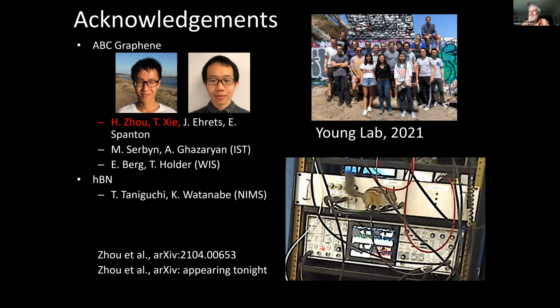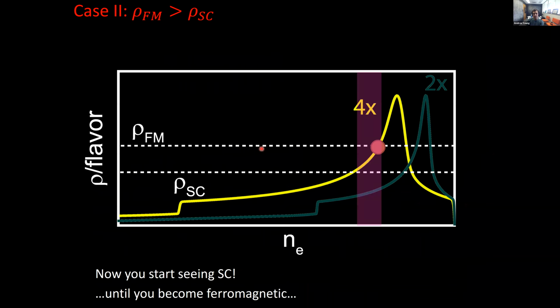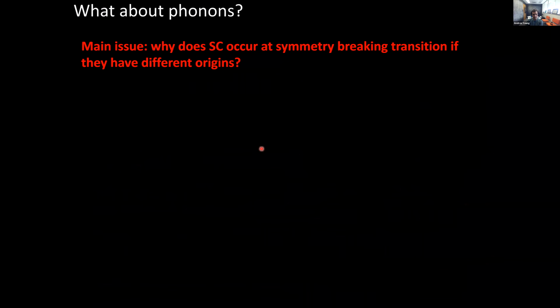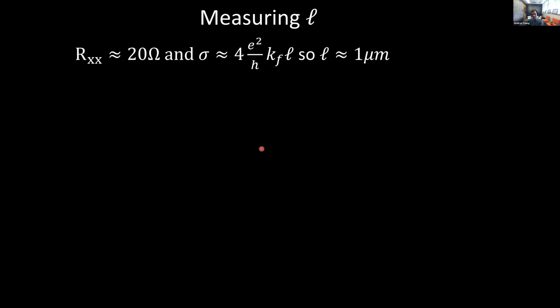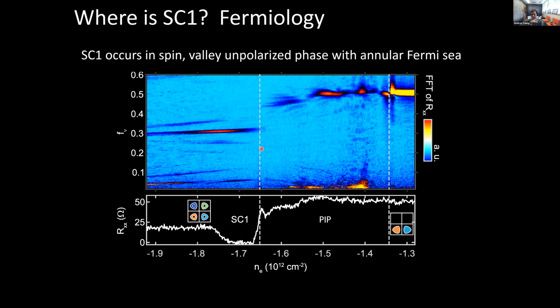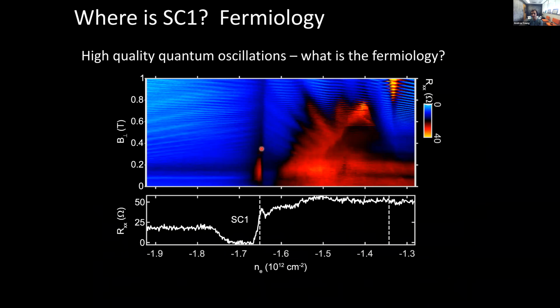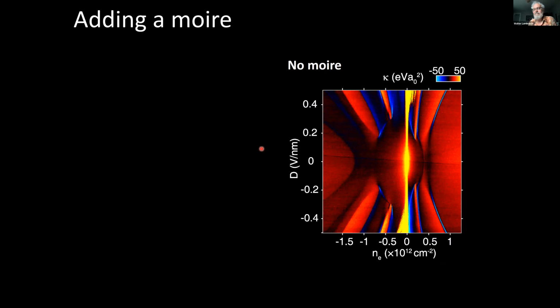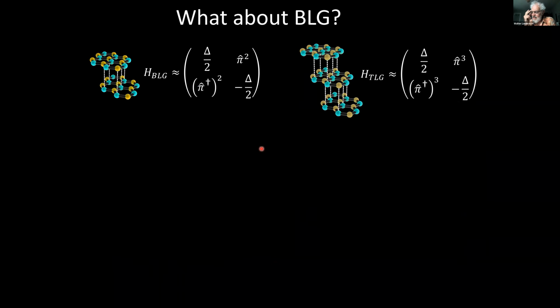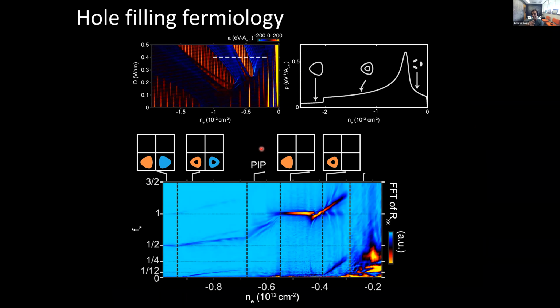Nice talk, very interesting. I have a few simple questions about the magnetism, not the superconductivity. The first thing is, what is the Curie temperature? Between 5 and 10 Kelvin. We haven't measured it carefully, but at 5 or 6 Kelvin, you already see many of the features in the density of states. We haven't found a sharp transition. So that gives me a scale. Yeah, that gives you the scale.